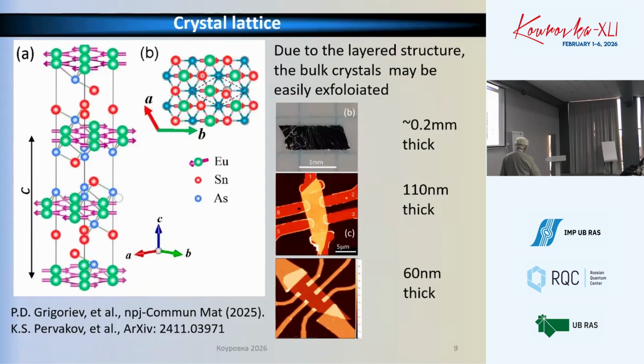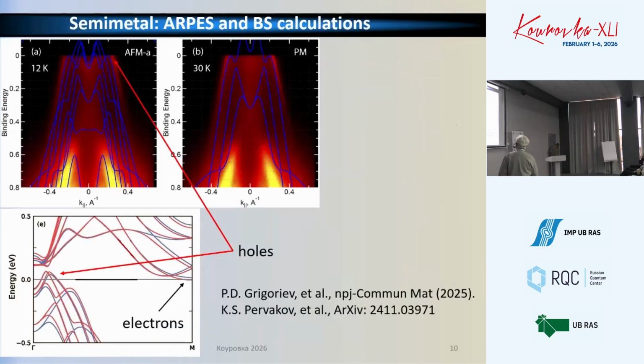Now, what I said is that the materials are layered, therefore they can be exfoliated. We grow the bulk crystals and exfoliate them to a thickness of down to 60 nanometers. It's about 25 atomic layers. The band structure, which we studied first of all, shows that there is no topologically non-trivial state. The band crossings are much above the Fermi energy, which is the zero level here, or below, but at the Fermi energy there is no feature that can be associated with topology. The calculated band structure also confirmed that this is a normal metal. There is a quite pronounced hole type pocket close to the center of the Brillouin zone, and electrons close to the periphery.